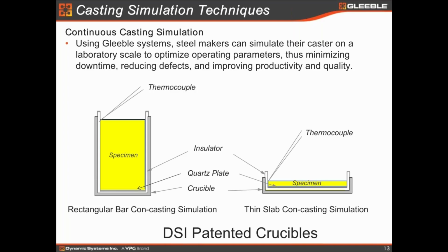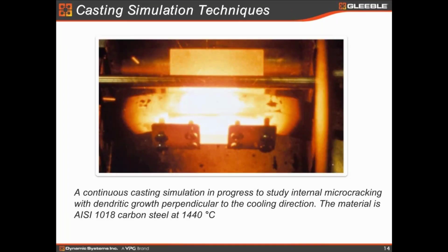And then later on, you can either pull it to check the microstructure or micro defects, and then you can even machine the sample out of it to do the deformation. And this can be thick, can be thin, up to whatever the sample that you have. So it's pretty convenient and very economical too. Okay, and this is a very good example of the casting process simulation.